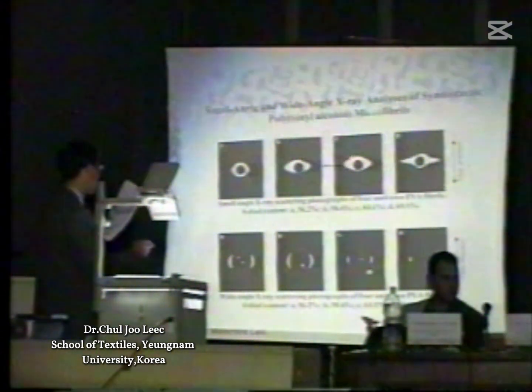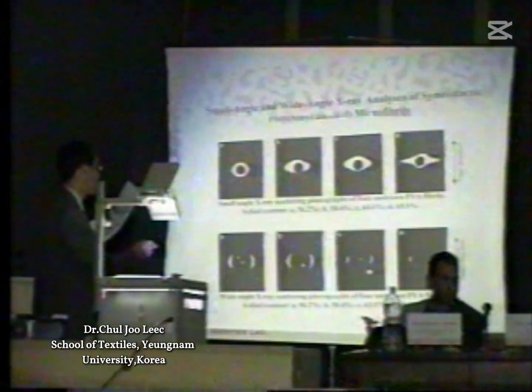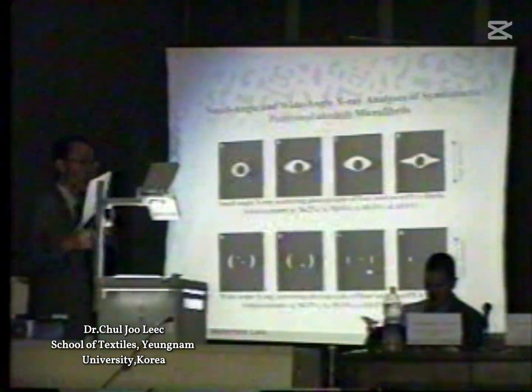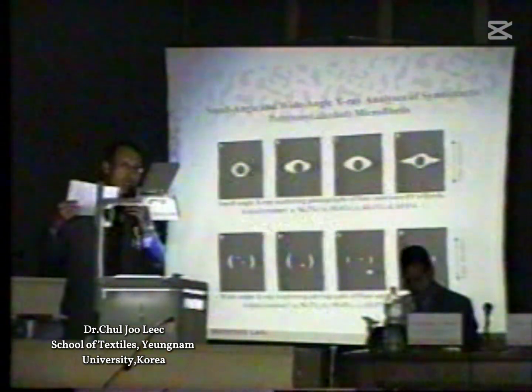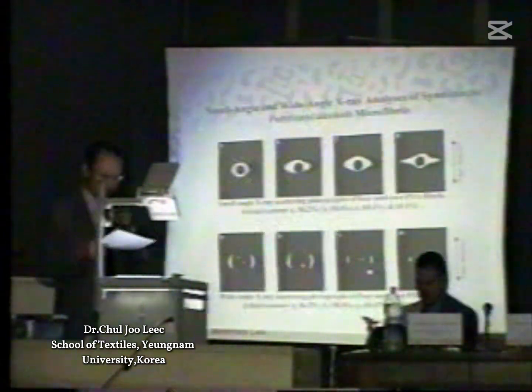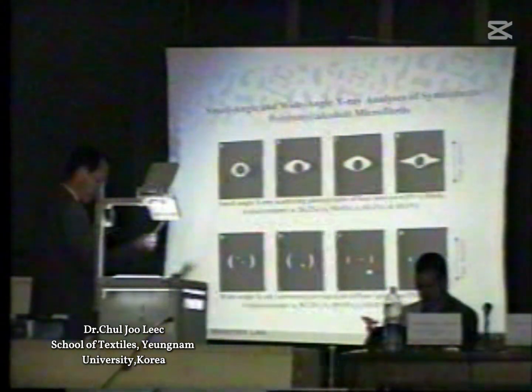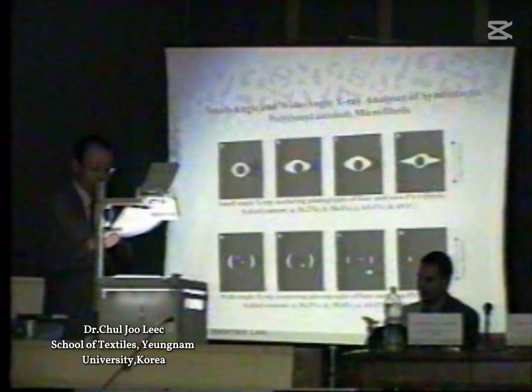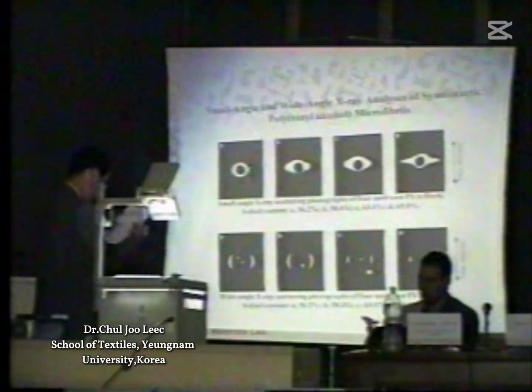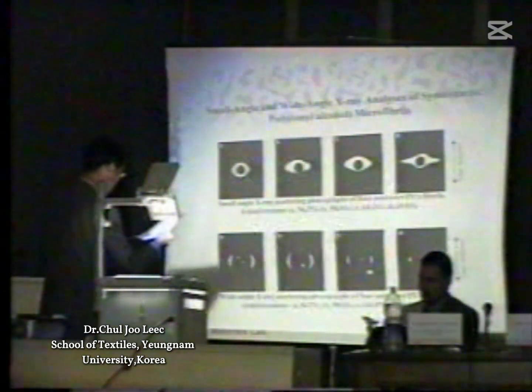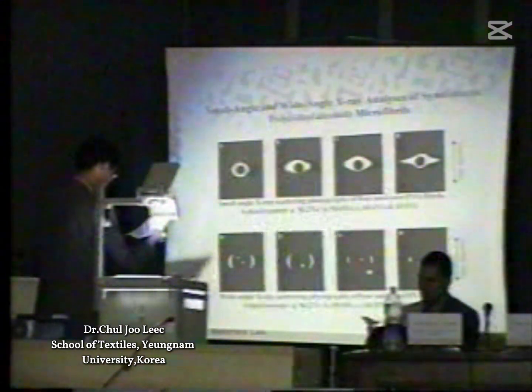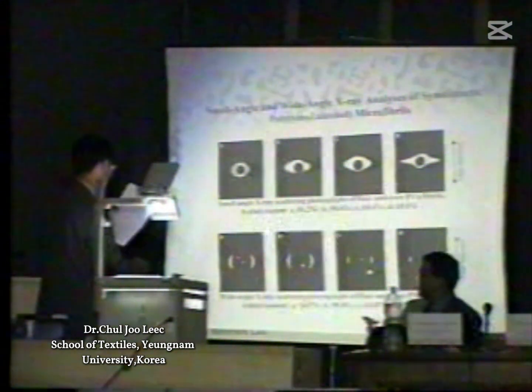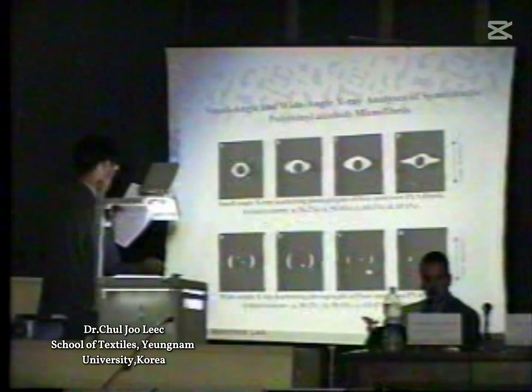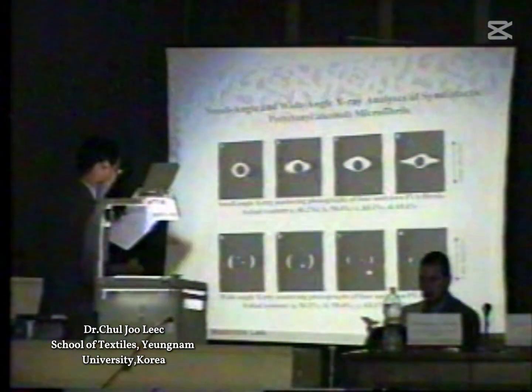The pattern becomes very slim, and it means that the microvoids become uniform and elongated. It means the PVA chains are better aligned with higher syndiotacticity. And next, from the wide-angle X-ray scattering, we can know that the crystal orientation increased with syndiotacticity, as you see from the patterns of these four X-rays.